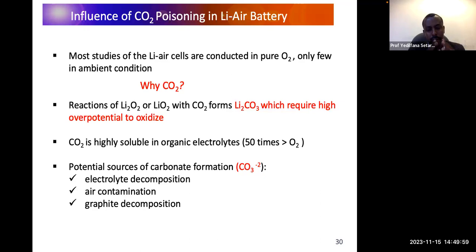The other thing is that there are three ways of getting carbonate formation. One is from electrolyte decomposition. If you remember, we have the electrolyte between the two electrodes. Usually in this battery type, we use a non-aqueous, aprotic, organic electrolyte. When it decomposes, it releases carbonate. We have lithium ion in our system, so lithium ion interacts with this carbonate and forms lithium carbonate. This is a problem because lithium carbonate cannot be easily oxidized once it is formed in the battery. The other possibility is from air contamination, as we already said. If carbon dioxide enters, then it can decompose into carbonate and form lithium carbonate.